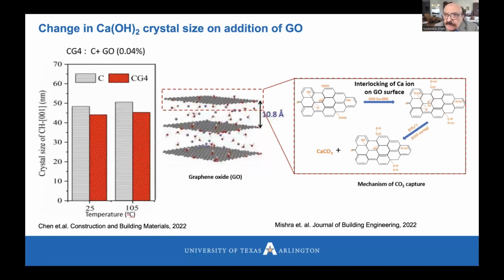Why does it do it? Why does very small amount of GO enhance carbon capture? Well, there are two reasons. At least there may be many we are understanding. One is that when we add graphene oxide, then after hydration, the size of calcium hydroxide crystal goes down. The smaller the size, higher the surface area, more carbon capture. Another thing is the graphene oxide, because of COOH surface charges, it captures calcium. And that, of course, enhances carbonation. So graphene oxide can be very, very helpful, very small addition in carbon capture and improving long-term properties of concrete.